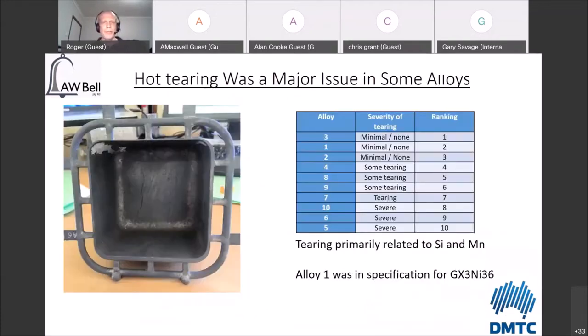One of the things that we found was that in a number of these alloys, hot tearing was a real problem. This particular one is number 6, which was the 9th worst rated one. And you can see the hot tear that runs through the part here. It has had the shell removed, but it's not been sandblasted or shot blasted or anything like that because I wanted to actually capture the hot tears.